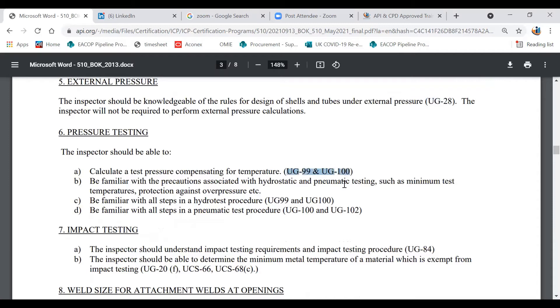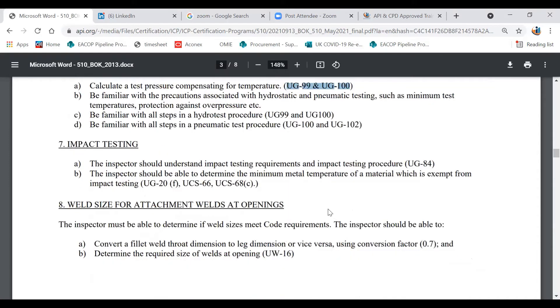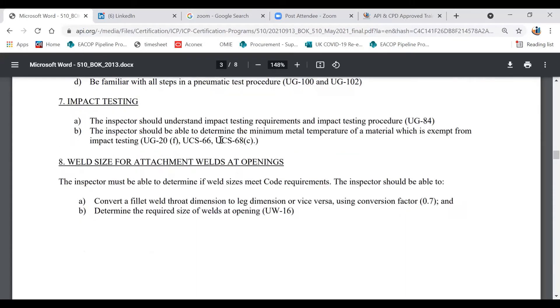You should know about pressure testing, which comes from ASME Section 8, UG-99 and UG-100. You should also know about impact testing, because metal behavior changes with temperature — the cooler it gets, the more brittle it becomes. Some pressure vessels have failed during pressure tests because the ambient temperature or fluid temperature was too low and the test pressure too high. The test pressure is normally 1.3 times, though many use 1.5 times the operating pressure, to verify the vessel can withstand operating conditions.